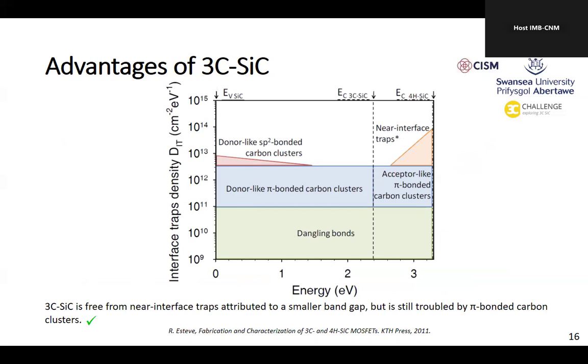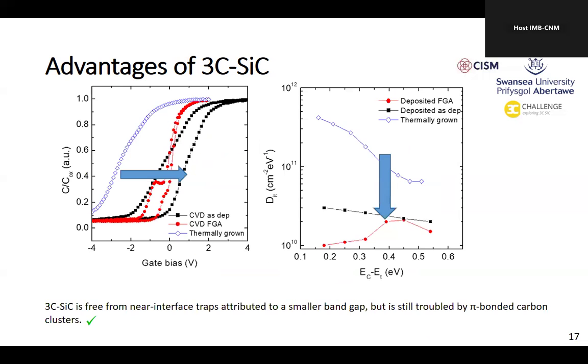Okay, that's one thing. And the other point to make here is that unlike 4H silicon carbide, cubic silicon carbide doesn't suffer from the really high density of NITs, near interface traps. And what's not shown on this diagram as well is the near interface oxide traps. None of that affects cubic silicon carbide because they're only affected by these donor and dangling bond type defects. So your channel mobility and your channel resistance will be much, much lower for this system compared to 4H.